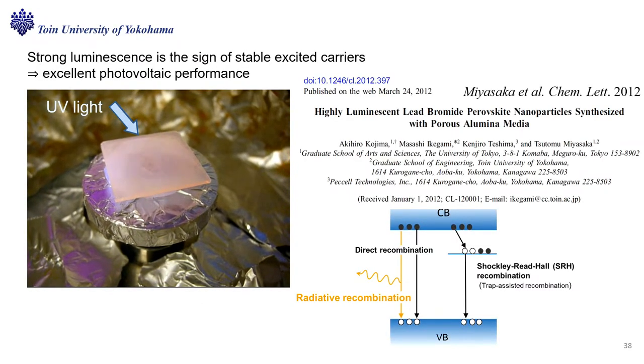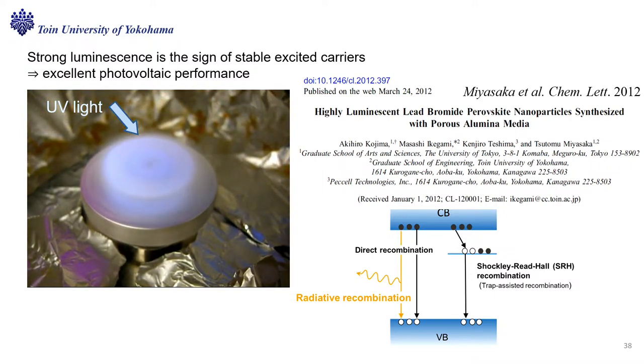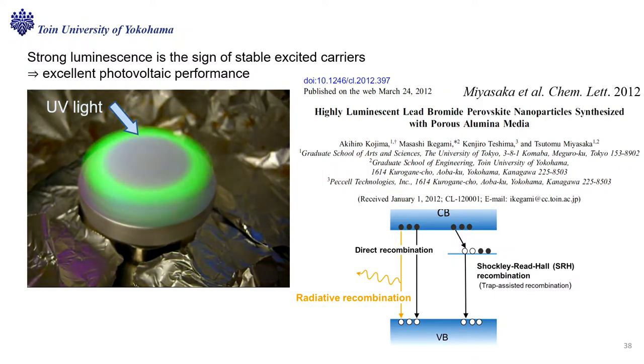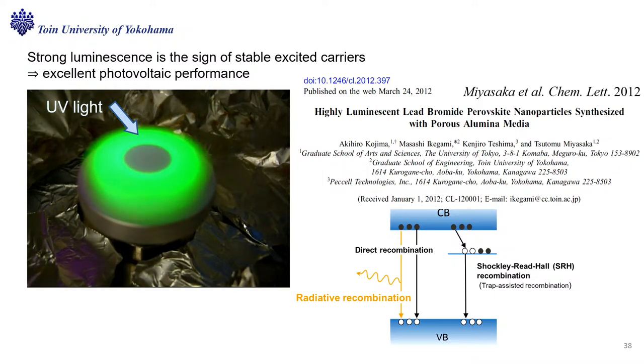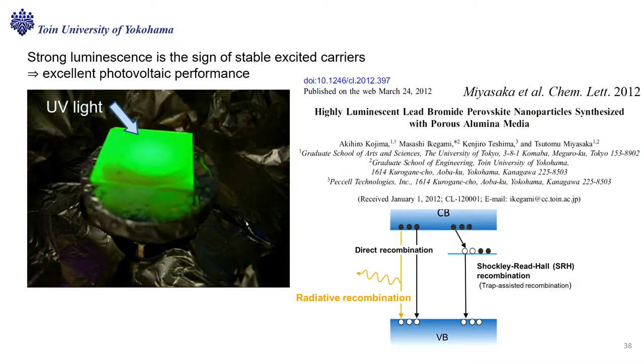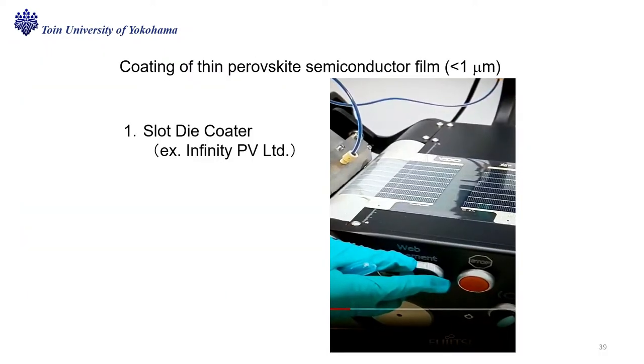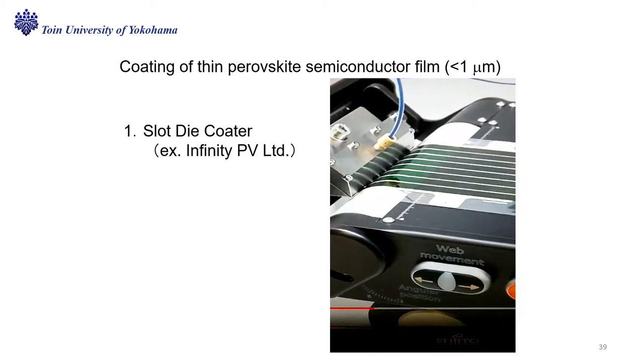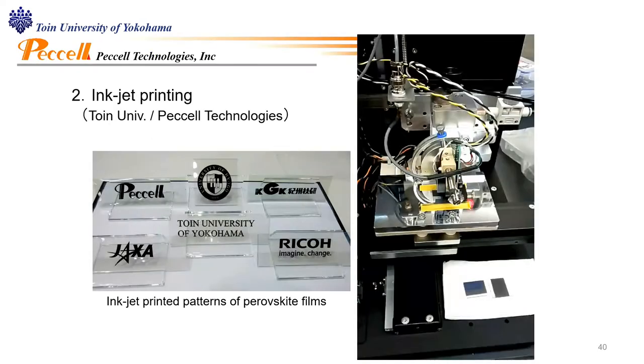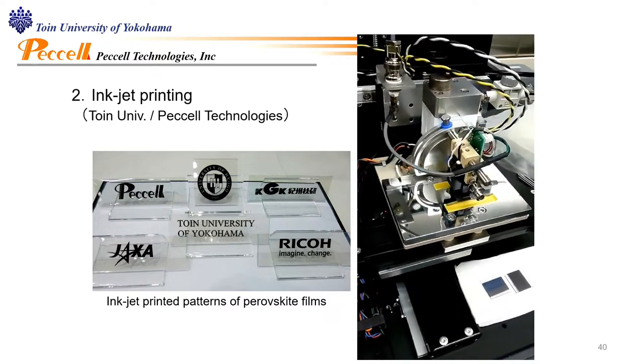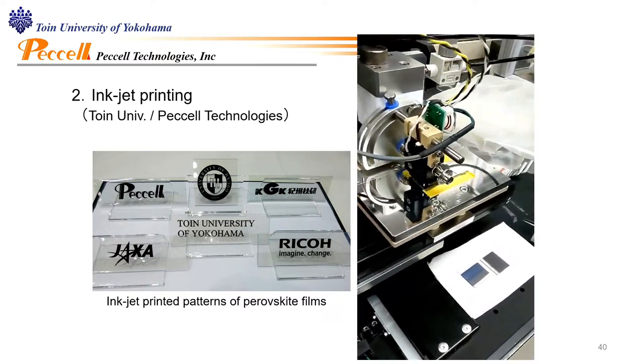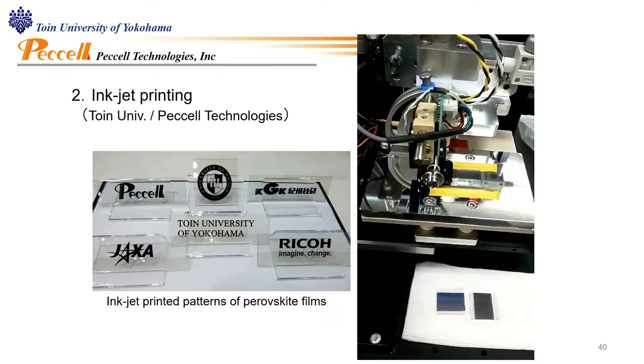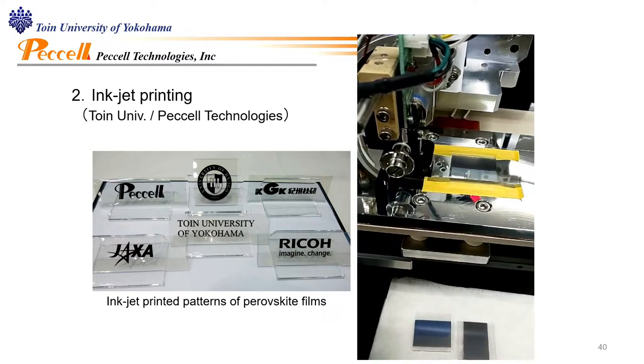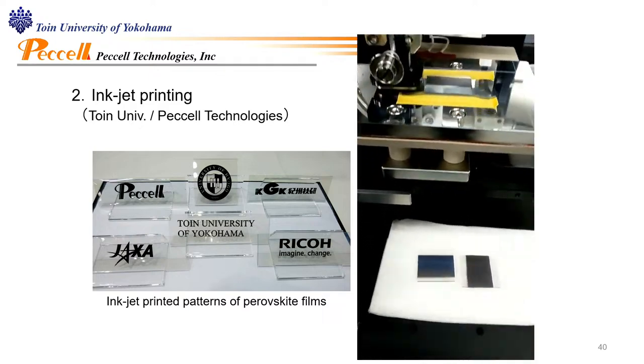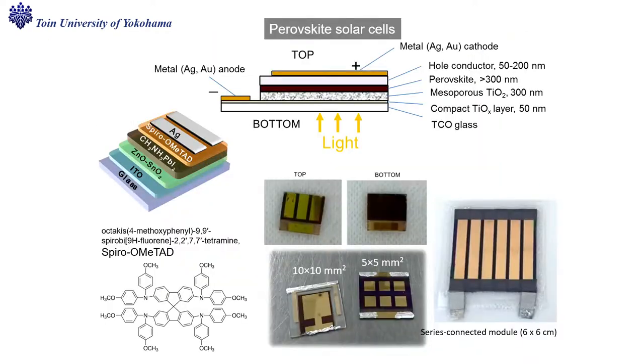So we can show this defect tolerance by shining UV light on the perovskite layer. When the solvent is evaporated and crystals are formed, we can see the vivid light emission from the perovskite crystal. This is a bromide perovskite. And coating is easy. This is how to coat a perovskite thin film by slot die coater. And we also developed a special inkjet printer in collaboration with a Wakayama Prefecture-based company, Kishu Giken. They developed the special ink and head of the printer. So now we can print any kind of letter and design on plastic and glass electrodes.